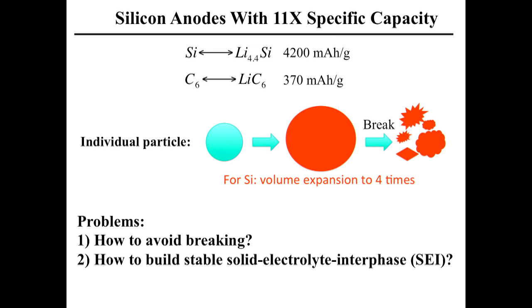So this is the phenomenon I was describing. Silicon takes a lot of lithium, 11 times of graphite capacity. Volume expansion to 4 times. Imagine that, that's a lot, right? If you look at the furniture, I remember when I was a little kid, summertime came, my hometown was very hot during summer, and then in winter it gets cold. It goes through this cycle, hot and cold, and the furniture actually cracked. That's only probably 10%. You're talking about 400% right here.